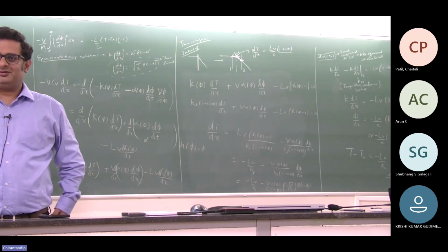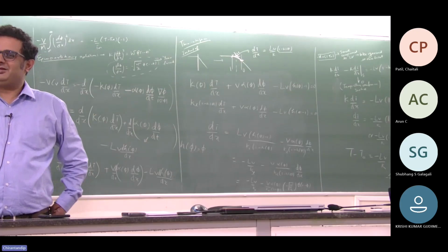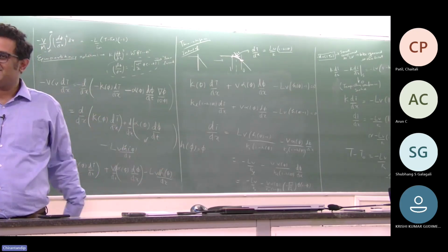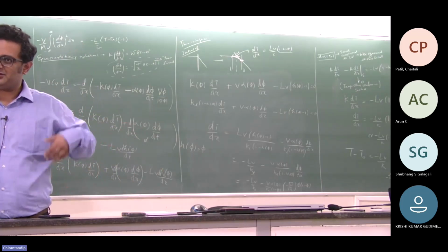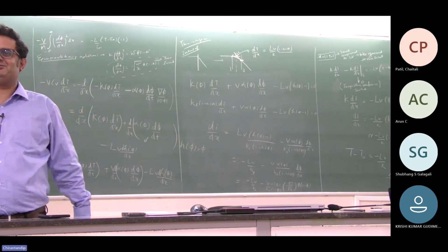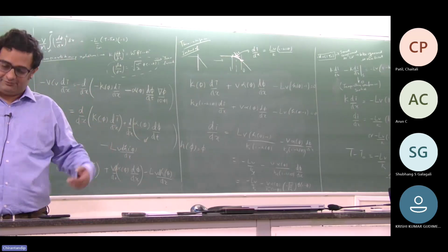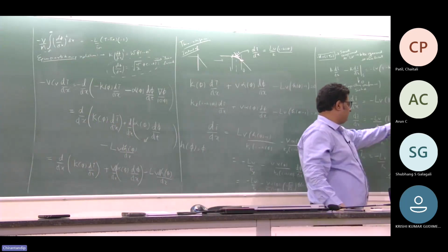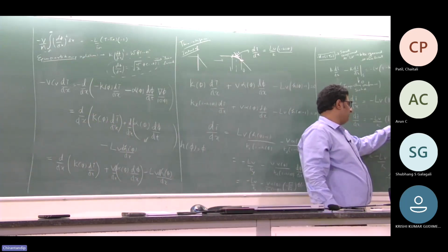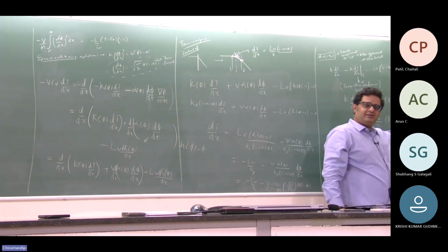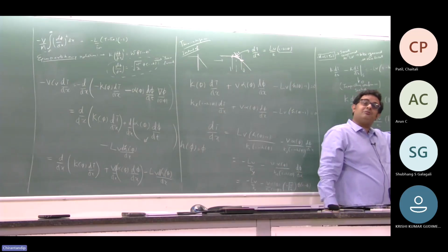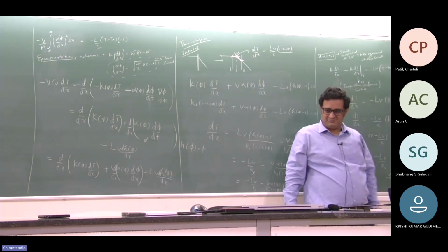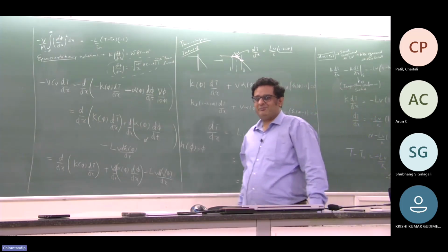But we have only taken that linear approximation, no? dT/dx. If you're interested in the parabolic approximation, you go to the second order asymptotics, or higher, and then that's still T star equal to T naught. You can still derive. I have stopped at deriving dT/dx as 1 minus a function of t. If I am looking for the second term in the parabola, which is t squared, I can derive it, and it will give you a different curve.